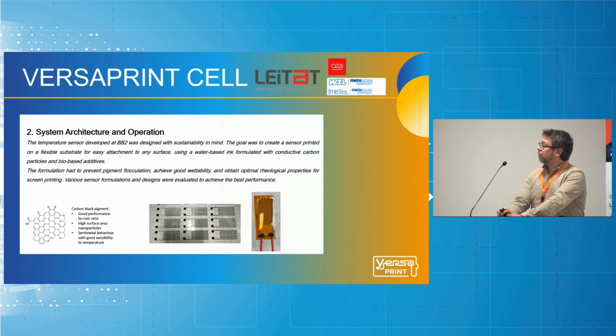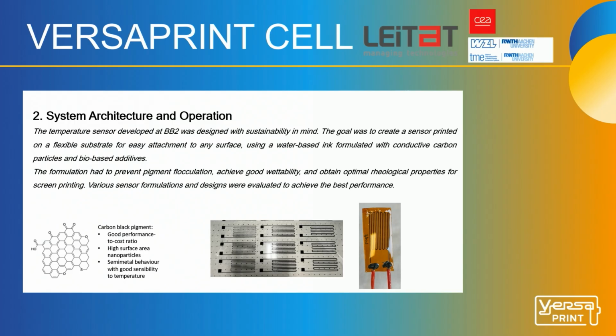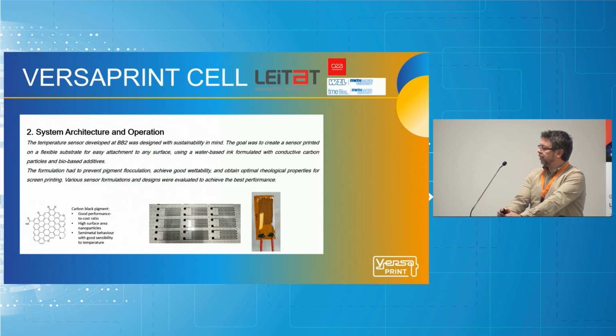The second technology was this temperature sensor for the BB2. It was designed with sustainability in mind. The goal was to create this sensor printed on flexible substrates to be easily attached to any surface, using a water-based ink formulated with conductive carbon particles and bio-based additives. This carbon pigment presents a good performance to cost ratio and a high surface area of the nanoparticles to improve the wettability and coalescence, and presents a semi-metal behavior with some good sensitivity to temperature. This ink was formulated to prevent flocculation, achieve good wettability, and obtain optimal rheological properties for printing by screen printing. Several configurations and geometries were devised to select the one with the best performance.